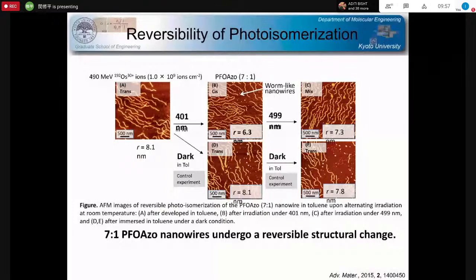And the further checking of the global morphology of the nanowires was also confirmed by successive light exposures. In this view graph, after the preparation of the straightforward one-dimensional nanowires, under ultraviolet light exposure the nanowires changed into the wavy form, as shown in the middle panels. And then they returned to the stretched form, as shown on the right-hand side.